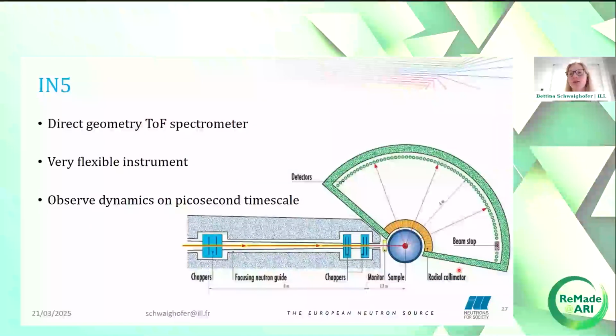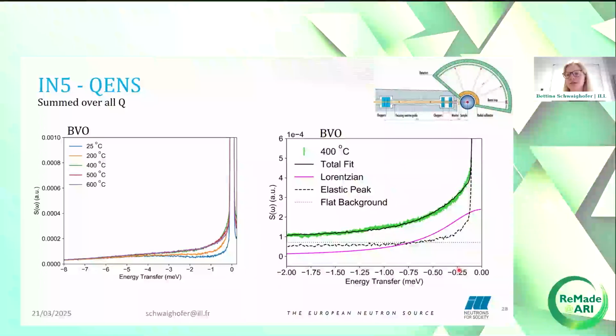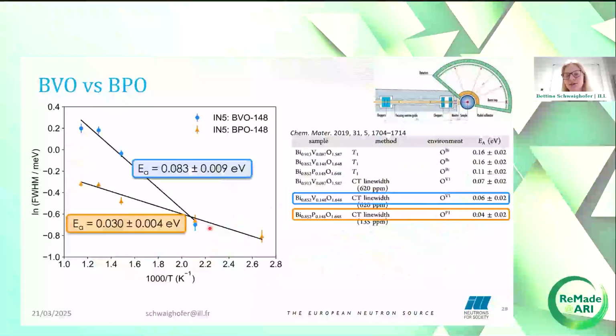To look at dynamics on a different timescale, we went to IN5, which allows us to observe picosecond dynamics. On IN5, we measured more temperatures, and as you can see, increasing the temperature significantly increases the broadening we observe. The data was fitted the same way as the IN16B data, with a convolution of the resolution and a delta function for the elastic peak and a Lorentzian for the QENS broadening. The data for BPO looks very similar to this and was treated the same way.